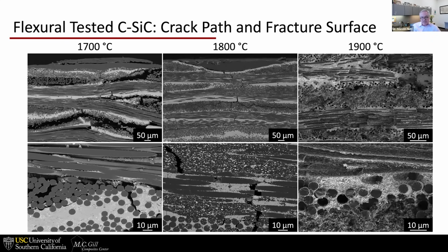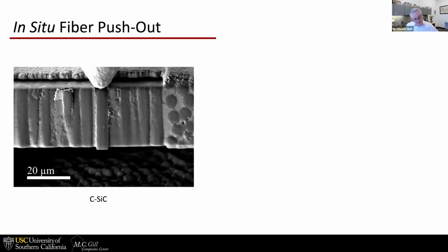But the result of all of this preliminary work has been to identify a process temperature, a sintering temperature that seems to work better than others. Measuring the interface strength is a really important challenge, but a very difficult thing to do. One of the approaches that we've used is